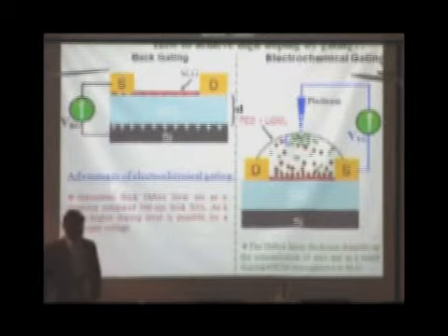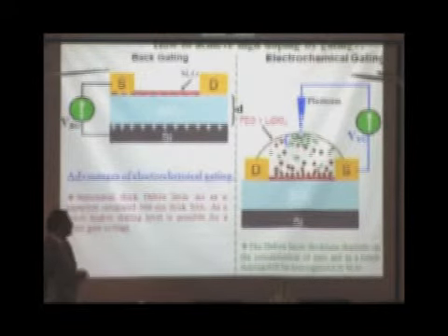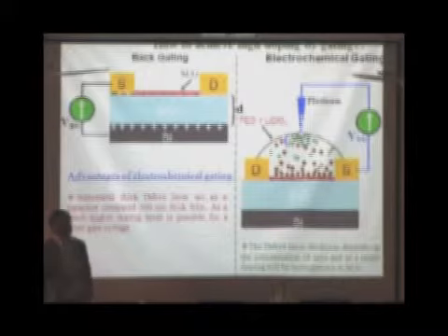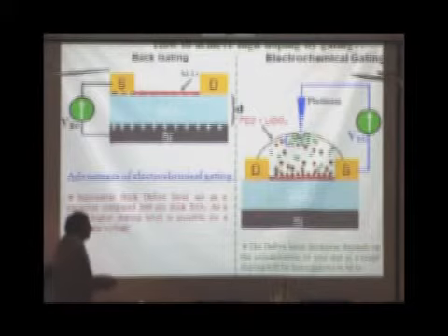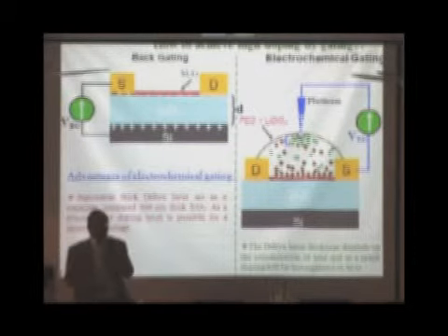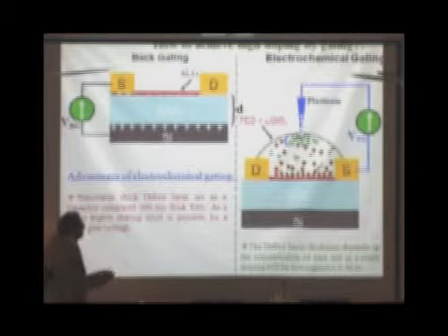What we have done is a small trick. It is known in the literature that you can do electrochemical gating. So instead of using 300 nanometer of gate, we don't use this. We put a drop of solid electrolyte. It is a polymer with lithium perchlorate. Now here, when you apply a gate, which is a platinum wire or a gold wire, between these two electrodes,